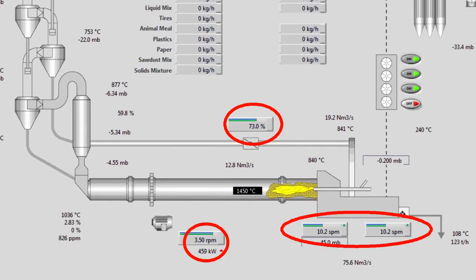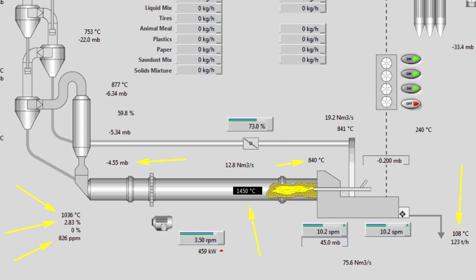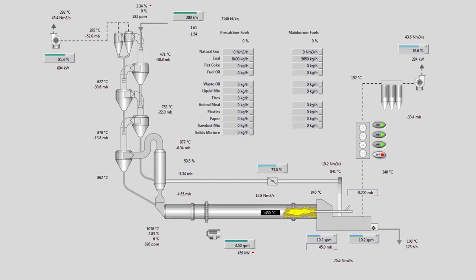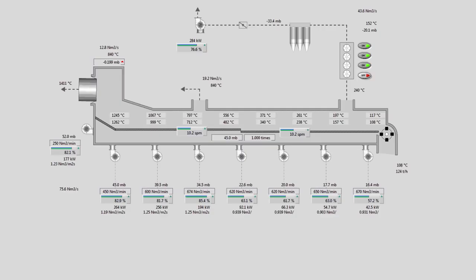The kiln runs at 3.5 RPMs. Tertiary duct is set at 3/4 of its position, and we can see there are 2 grates on the clinker cooler. Here as well, take note of the temperatures and pressures of the system. Notice in particular a good burning zone temperature, nice secondary temperature, and a very cool clinker temperature exiting the cooler. Looking at the cooler, we see 8 undergrade fans, 2 grates, and the usual control loop between waste air and kiln hood.